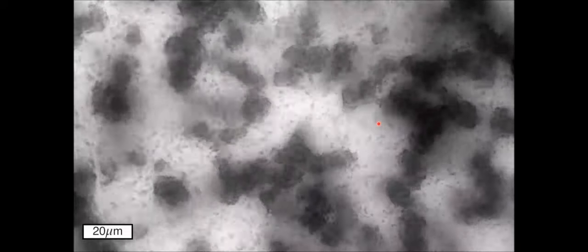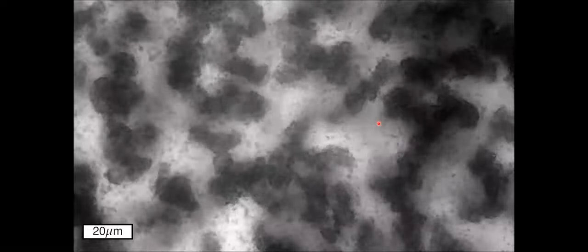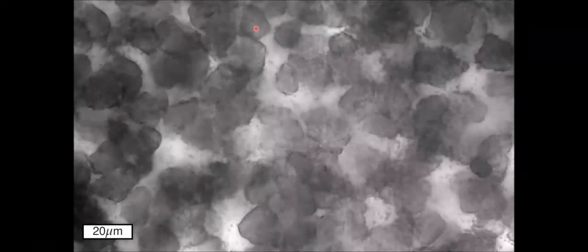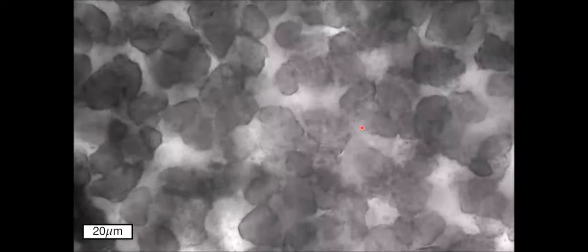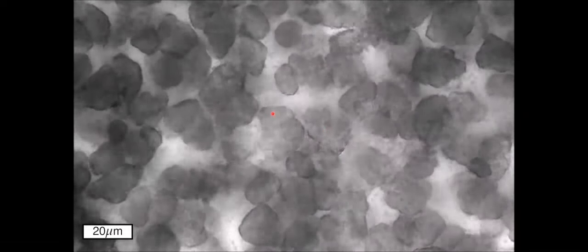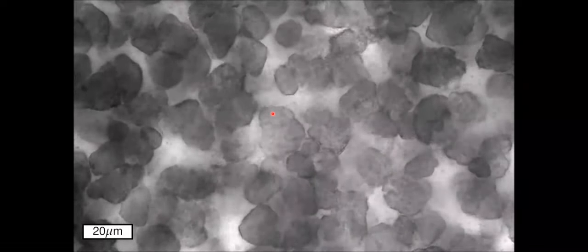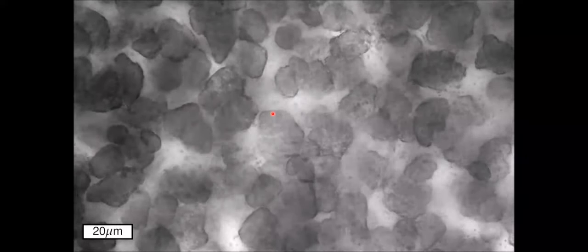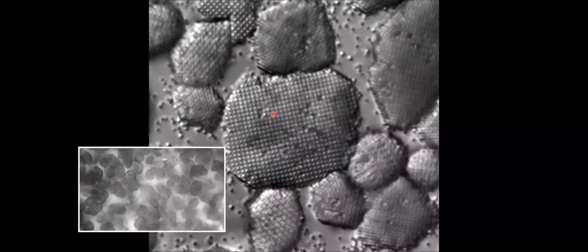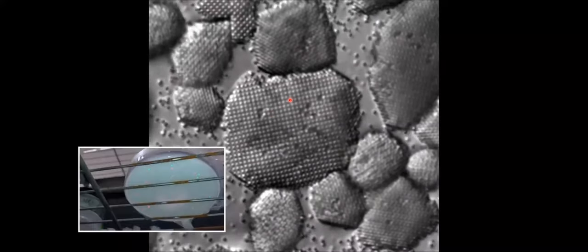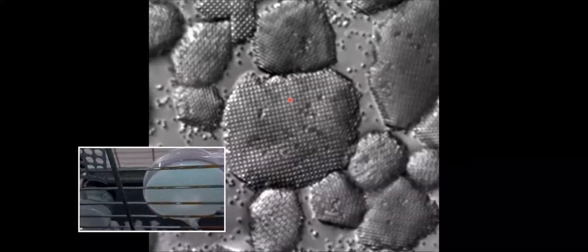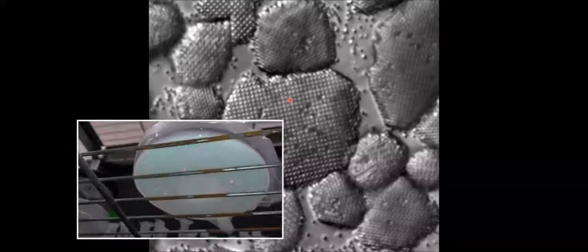Okay, and so this is what it looks like live. This is a very dense suspension. This is like 5% weight particles. And so it looks a little chaotic. It looks like there's a bunch of aggregation to start with. But then some islands start to pop up that look not like something totally disordered. And as those crystals start to grow and consume all the background particles, you can really see the suspension start to clarify. And we can see that these are all domains. These are each a different single crystal domain. When I have a more dilute sample, we can see much more clearly individual particles and crystalline planes, which is coming up now. And this is actually a sample that's been in a capillary reconfiguring for months. So this dance is just never ending, constantly finding the lowest energy and very stable.